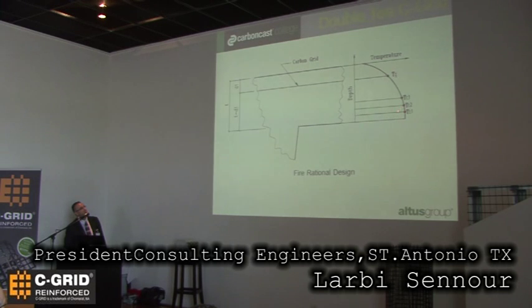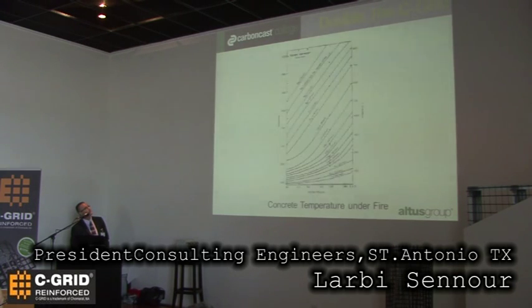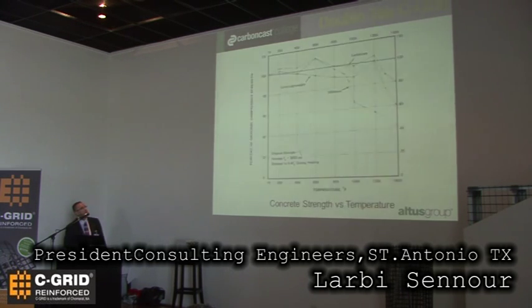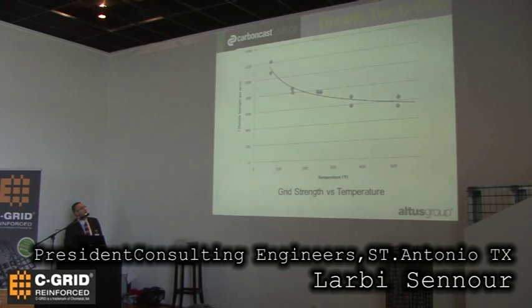We will have temperatures, if you're doing for 2 hours, you come up with your temperatures at a variation for concrete, and then the temperature at the grid. Based on the temperature and the type of concrete and the cover, you can get a strength reduction for concrete. So you get your strength reductions. And then for the grid, we have our own curve, depending on the temperature. This is in degrees Fahrenheit. It gives you the reduction.